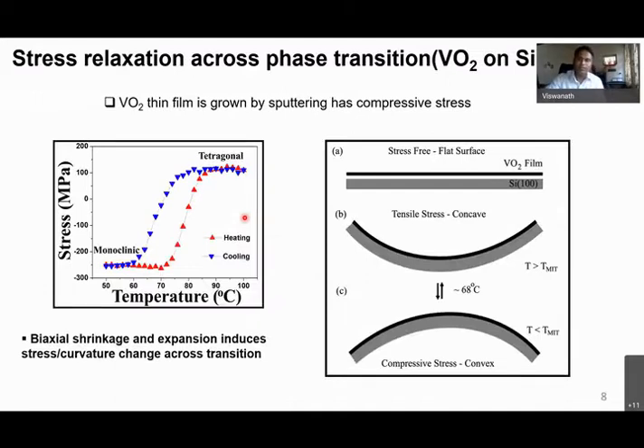So after depositing a thin film, for example, the thin film which is not attached is going to be stress-free. The moment you attach it to the substrate, of course, there is going to be a stress imposing a curvature. Now, imagine the thin film, in this case vanadium dioxide, or shape memory alloys like nickel titanium. They are going to undergo phase transformation during heating and cooling. Because of the heating and cooling induced phase transformation, there will be a volume change. That volume change would induce a reversible change in the curvature.